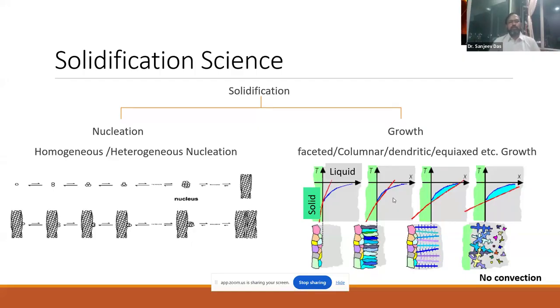What is homogeneous nucleation? In the liquid, the atoms will come together when the temperature drops, and they will form a cluster. Initially one cluster will form, but there will be latent heat release, so this cluster will break up again. As you drop the temperature further, more atoms come closer, making a bigger cluster. And when a nucleus of critical diameter is formed, then the growth starts. But in heterogeneous nucleation, there is always a surface, and on that surface, atoms from the liquid come and sit, and then slowly grow. Heterogeneous nucleation always takes place because it is very easy to happen. Homogeneous nucleation is very difficult.